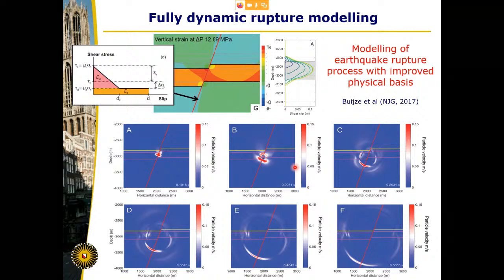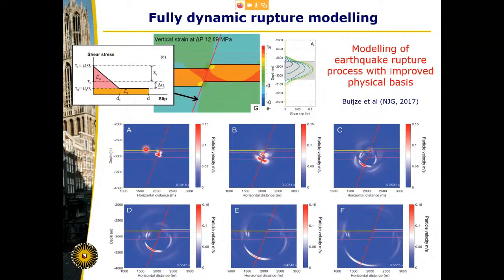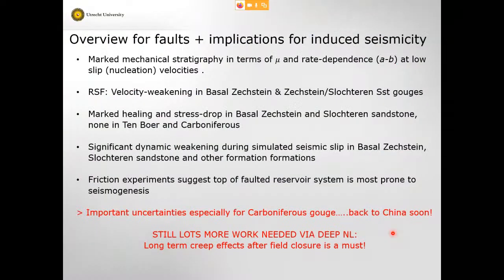The results of those friction data have been put by Loes Buijze in her PhD thesis into purely dynamic models, as well as quasi-dynamic models, of rupture modeling of earthquakes, producing earthquake waves. That's where it all ends up going. So the end of the story now essentially is, I'm cutting lots of corners here, we've characterized the way the sandstone behaves. It has a substantial amount of plastic deformation, which is important for understanding the evolution of stress and strain. And we've got a much better description of the strength behavior of the faults and their proneness to earthquake generation, if you like.